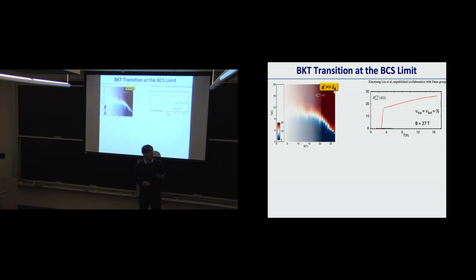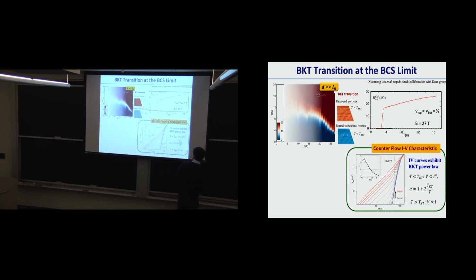Readily in the two-dimensional superconductor, this can actually be observed by just looking at the current and voltage characteristic in the condensations. Indeed, when we actually measure the current and voltage characteristic in the counterflow geometry, it more or less follows what is expected in BKT transitions.